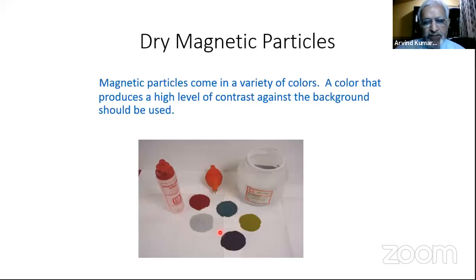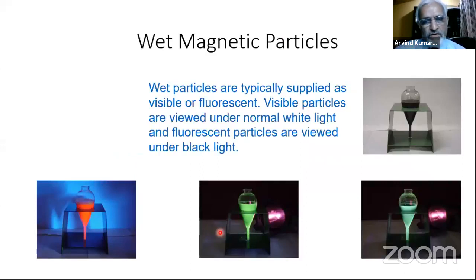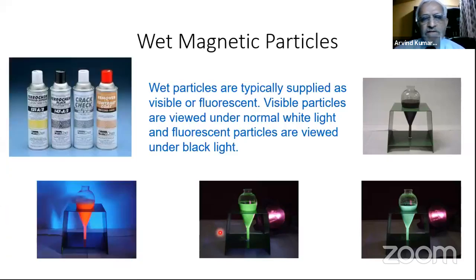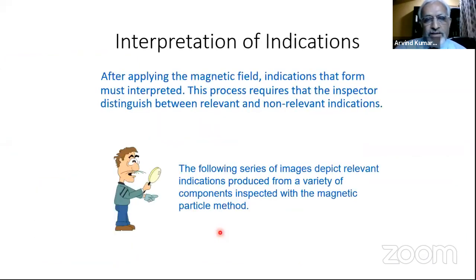For dry methods, you get dry powders in different colors like this. Now you can make a mix of wet particles also, with some concentrations available in the market, where you mix particles and then rotate in the centrifuge for half an hour and check the settling velocities and all that. But the easiest way is to use these aerosol cans, where again you have a cleaner and your wet particles, which you can apply straight away. Very easy to maintain. But if you are preparing particles like this with the centrifuge and all, a lot of other controls are required, which we should avoid.